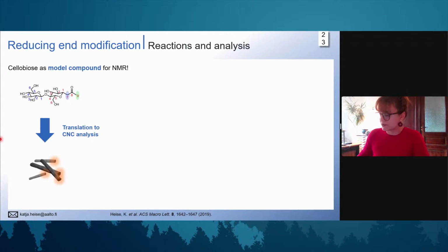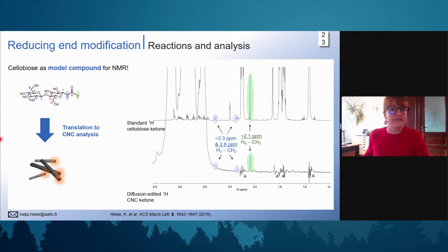Once this works, and the reaction works, you can translate the conditions and the analysis to cellulose nanocrystals. And then we have, on the top still, our standard proton spectrum of our cellobiose with the identified signals. And on the bottom, you have the diffusion edited spectrum of our CNC ketone, where you can identify the same signals, of course, with a far lower abundance. And now the interesting question is, because as I said, we can quantify with our method, can we actually really quantify?